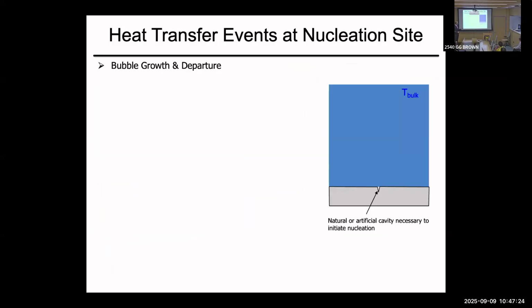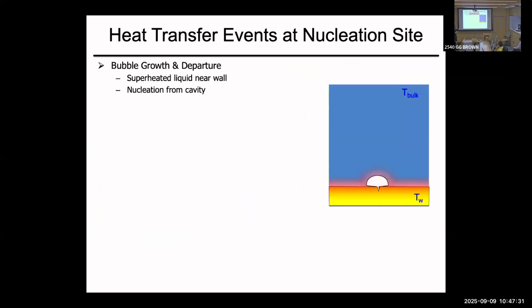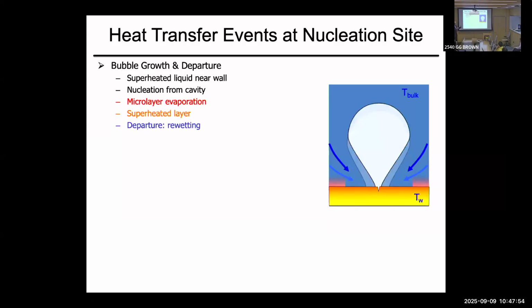If you look at nucleation, heat enters the fluid, a layer forms, and nucleation of the bubble happens. There is a film due to nucleation: a film of liquid is entrapped below the bubble and evaporates into the bubble, contributing not only to the heat transfer from the surface, but to the growth of the bubble. Then the bubble gets heat from the surroundings and ultimately goes up and departs, and liquid comes and rewets the surface.